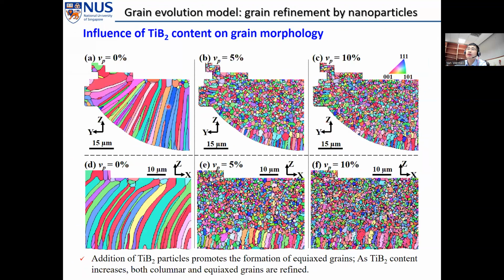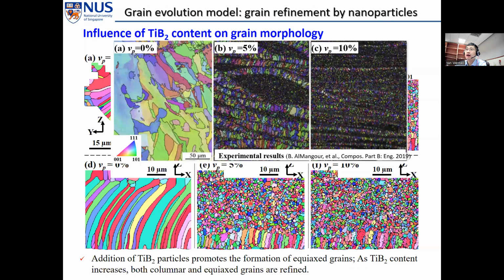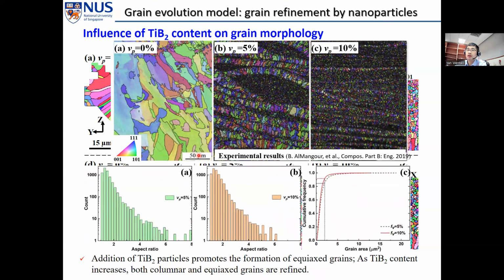When there's no nanoparticle, you can see it's mostly columnar grain. And with the addition of nanoparticles, it's a short columnar grain in the boundary and equiaxed grains in the middle. So this agrees well with the experimental results in literature. And we also compare quantitatively on the grain aspect ratio and grain size.